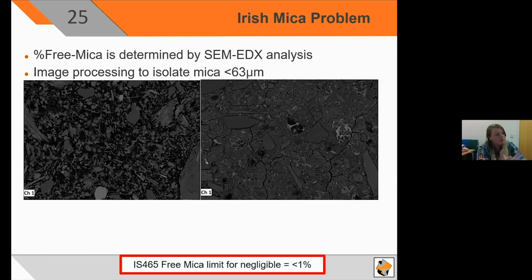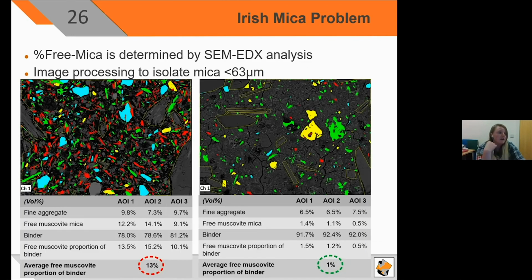So as Bradley said before, we determine free mica using SEM analysis and image processing software to isolate the free mica. So if you look at this image and then I superimpose the imaging software, you can see the one on the left lights up like a Christmas tree. The red is your free mica, and that derives a percentage of 13%. That is your free mica percentage. The one on the right, which is the China clay waste with the visible mica, there is no mica that is less than 63 microns. There's barely any. So that's 1% and would be given a negligible classification at IS 465.